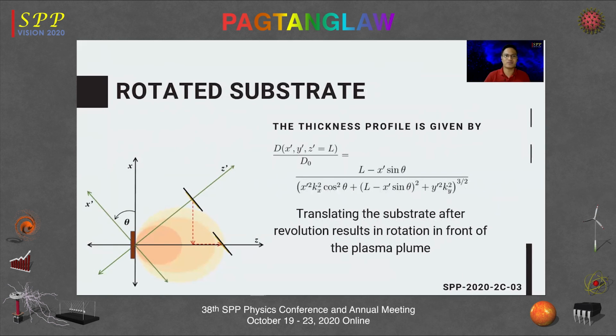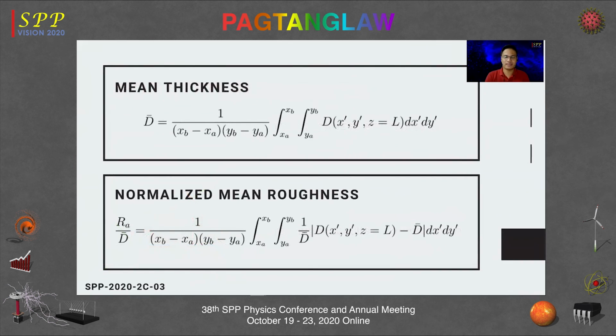On the other hand, for the rotated substrate, upon this coordinate transformation, we also translate it back to its initial position, which effectively allows a substrate that rotates in front of the plasma plume. And this is the equation for the thickness profile as a function of rotation angle theta. Now, in order to quantify the thickness profiles as a function of angle, we define the mean thickness as follows. It's just an integral of the thickness profile across the surface of the substrate divided by the area of the substrate. So this is the mean integral for that.